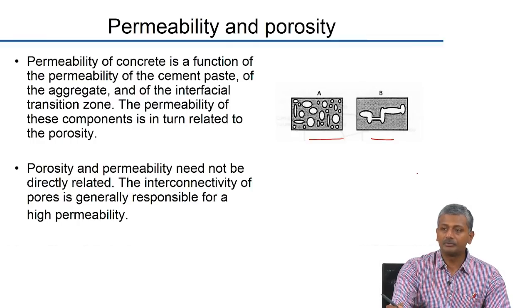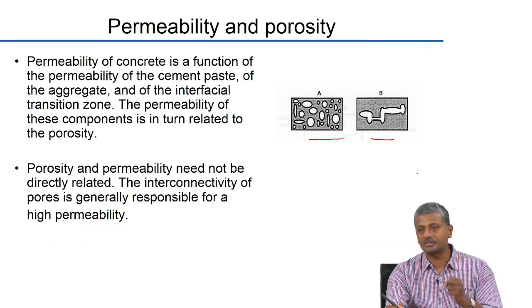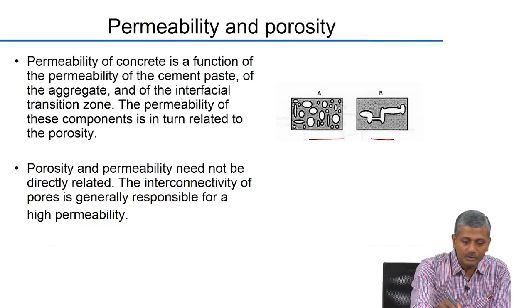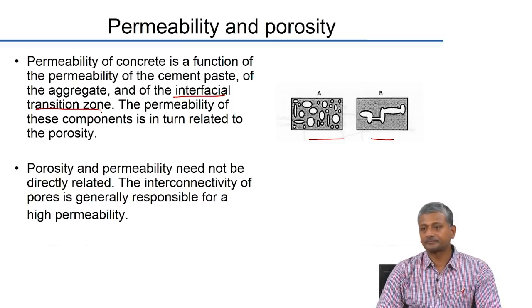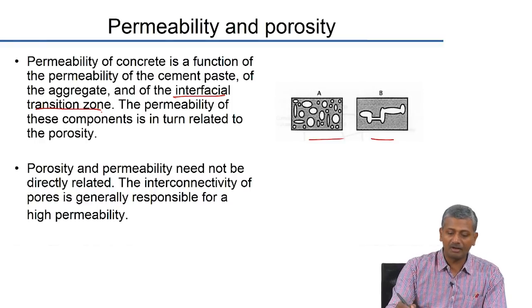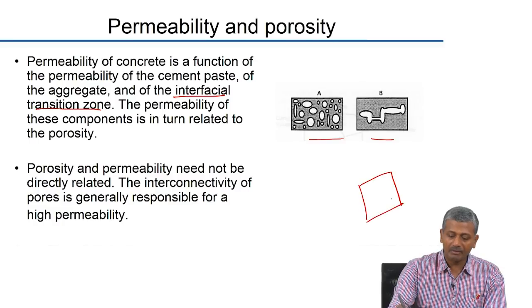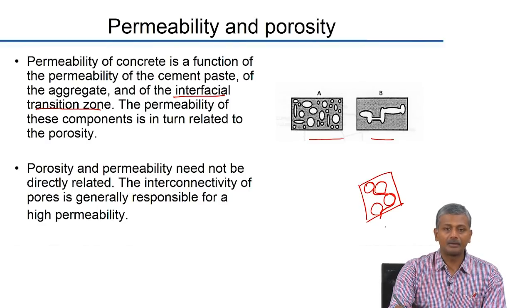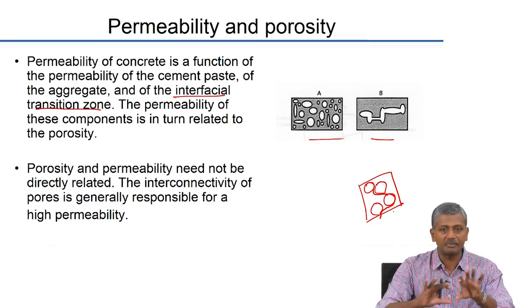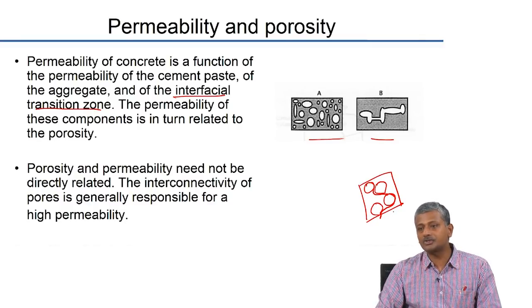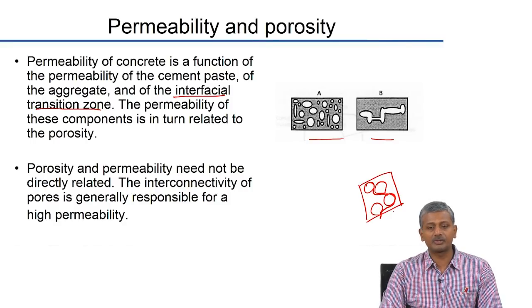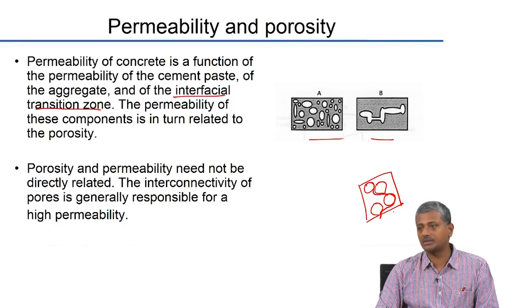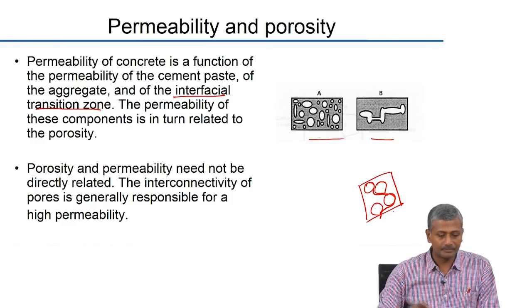Okay. So, porosity and permeability of course not just depend on water cement ratio of the paste, they also depend on the ITZ, and this we have discussed before, that when you have percolation of the ITZ, when you have ITZ that is close by, you can create a channel of flow through the concrete quite easily. So, that is why when we design high strength concretes, we choose higher paste contents so that we can separate the aggregates further, and that leads to the interfacial transition zones that become discrete. They are not connected to each other, that reduces the permeability significantly.